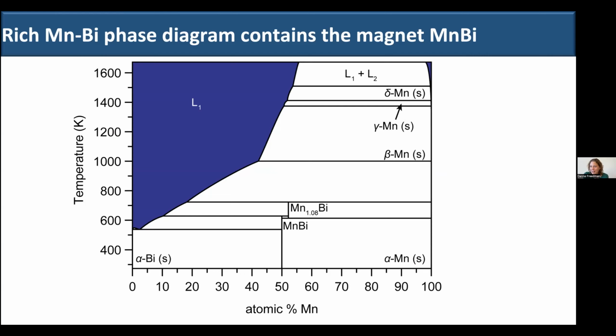It's a beautiful magnet. It crystallizes nominally in the nickel arsenide structure type, but it has all of these very weird properties. So for example, the hysteresis widens as you increase temperature, which is not generally observed in any material. So manganese bismuth, and the magnetic structure was only determined within the past 5 years, I believe, with neutron data on a single crystal of this material. So manganese bismuth is fantastic, but it makes no sense.